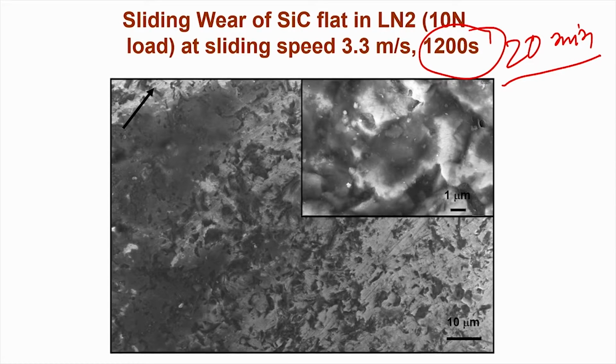If there is a difference in the leveling of the top surface, then, ceramics being brittle materials, when the disc experiences high sliding speed against the stationary ball while rotating, there is every chance the ceramic disc will break into two pieces.